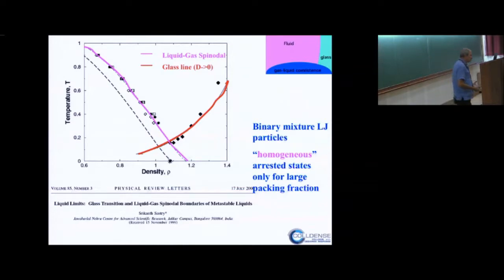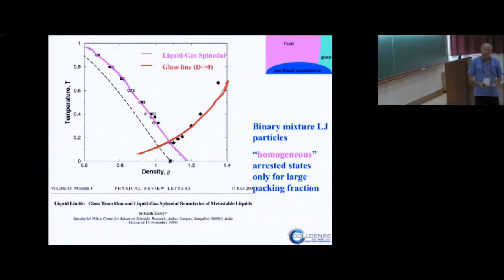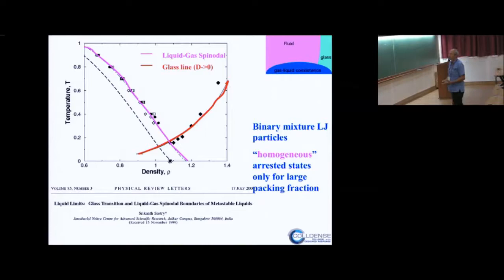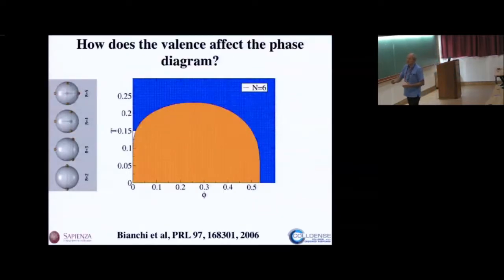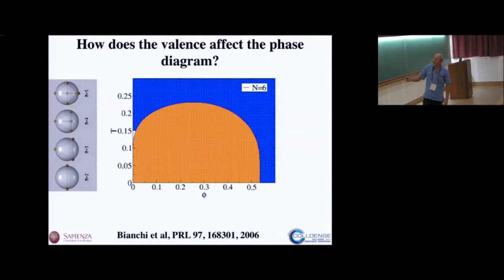So we started this project with the idea of how we can design an interaction potential in such a way that we somehow suppress the gas-liquid phase coexistence. We started by studying these patchy colloidal particles. You can think of these particles as simple hard spheres decorated with some attractive spots. So when two spots are close by, closer than some cutoff distance that you can fix, it's going to be like an angular square well interaction, let's say. Then those two particles will form a bond between the two.